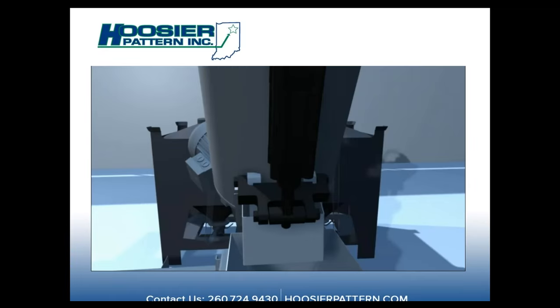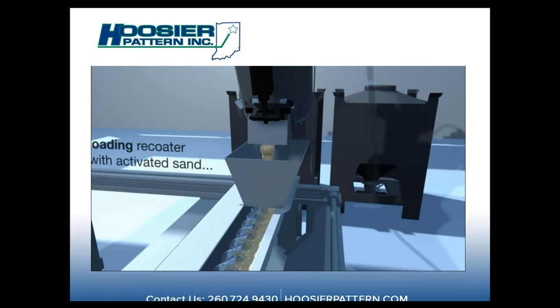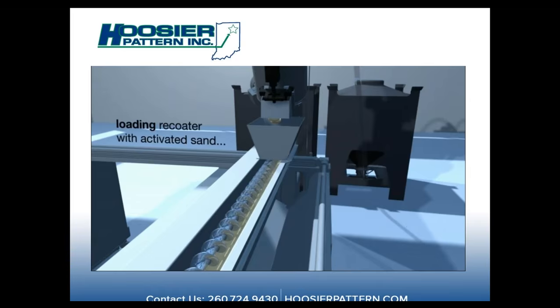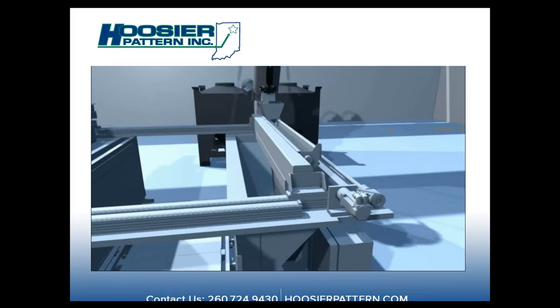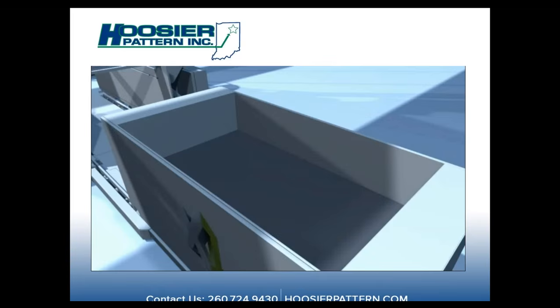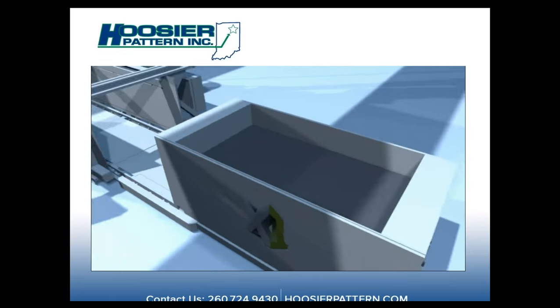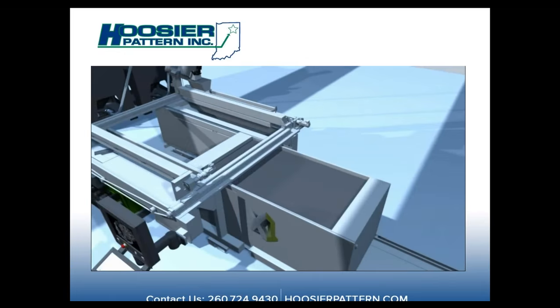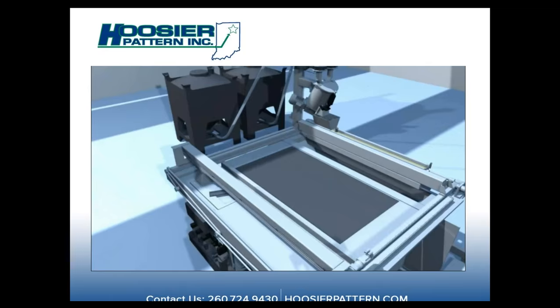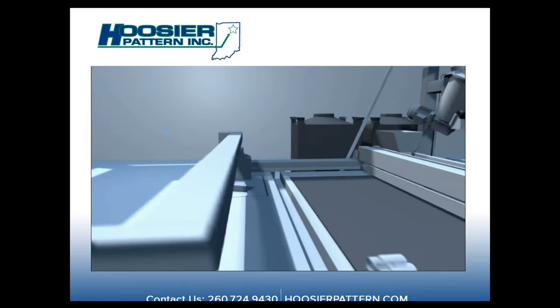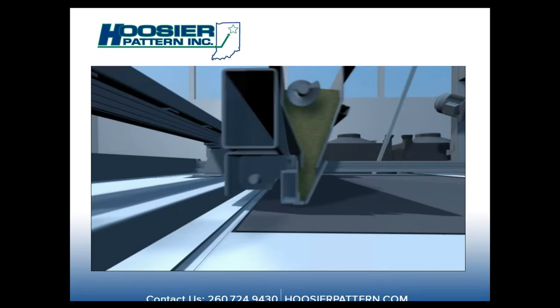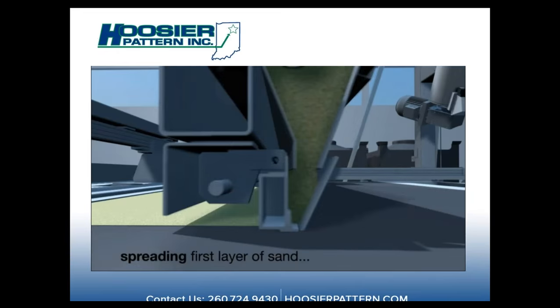It is then spread onto the machine in a thin layer. And right now you can see there's a job box going in. You can see where it filled into the recoater. And here in a second I'll show you actually laying the layers. So every time it prints a layer, that box actually drops 10 to 11 thousandths.